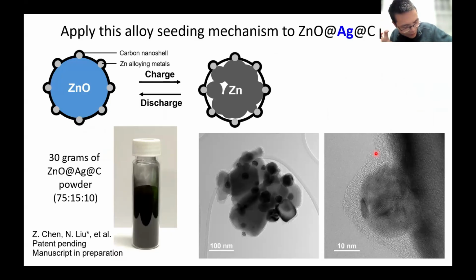And after we learned the principles of the alloying mechanism, we actually applied it back to the particle structure that you have seen earlier. The difference here is we place the silver nanoparticles on the inner surface of the carbon shell. So even though zinc over time slowly escapes out, because the silver is inside the particle, the escaped zinc will prefer to come back and deposit inside the carbon shell. So that actually actively brings them back, even though over time they slowly escape.